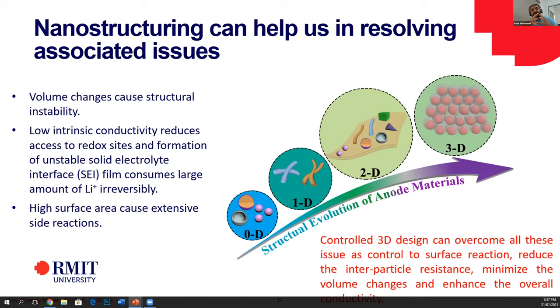So how can we improve the stability of the material? Different kinds of approaches have been tried. Previously it was thought that if we can reduce the size and make nanomaterials, we can have more active sites available and less volume change will happen. But reducing the size creates many other issues, like a thick solid electrolyte interface film formation and many side reactions. Then we moved towards 1D. We found something better, but not very exact.